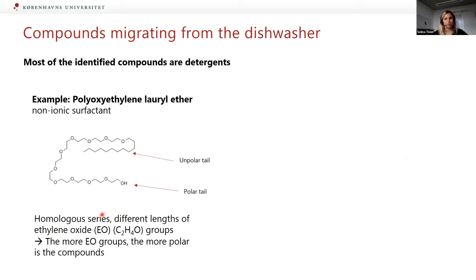Which are these compounds migrating from the dishwasher? Most of the identified compounds were detergents. What you have just seen, this chromatogram, is nice, a homologous series. One example are polyoxyethylene lauryl ethers, which are non-ionic surfactants. They have an unpolar tail with methyl groups and a polar tail with different lengths of ethylene oxide groups. So the more of these ethylene oxide groups there are, the more polar the compound is.